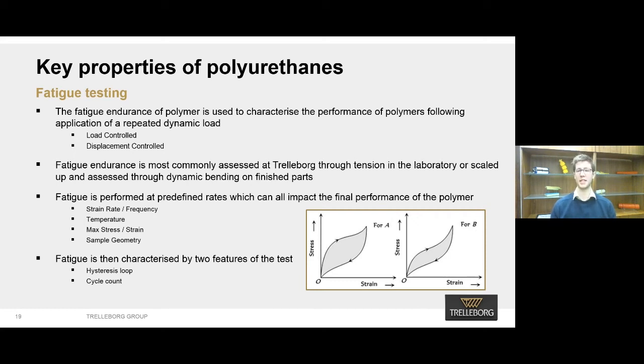We perform fatigue testing on a full size scale to validate a design or the final product, done to replicate its service conditions. An entire lifespan of a material is mimicked in a reduced time by increasing the strain rate and the frequency of the test. We validate designs for 25 years in service in just a few months or a year of testing. We characterise the fatigue test by how many cycles have been performed alongside a hysteresis loop — an example of which is seen on the bottom right of your screen right now.